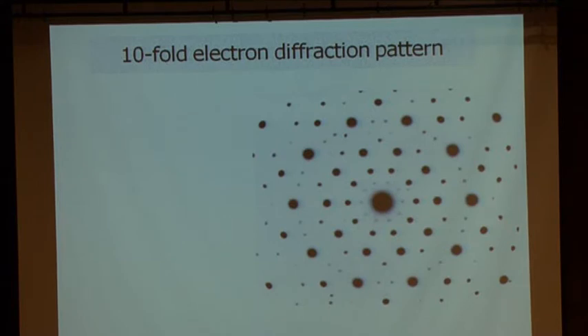Number one, if you count the number of spots, as I have done at the microscope, around one of the circles, then you will see that there are 10 spots. And if I had a good laser beam, which I don't, then I could even count it with you. But so I counted one way. I said, 10? No, cannot be. And I count the other way, tenfold, and this is what I wrote in my logbook. Another thing that was very strange, tenfold is forbidden, remember?